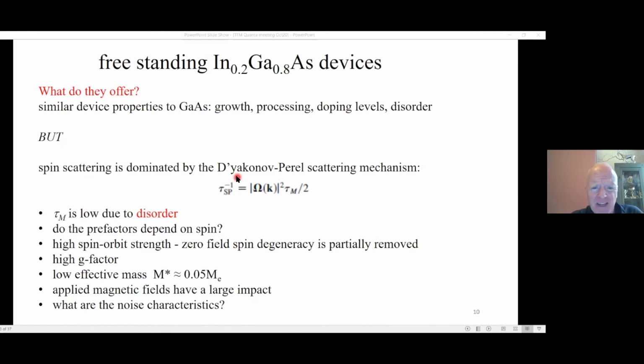In InGaAs, the spin scattering is dominated by a so-called Dyakonov-Perel scattering mechanism, and the spin flip rate, this quantity here, is determined by the spin precession from the Rashba component in the Hamiltonian, and it's also proportional to tau_m, which is the momentum relaxation time. So the momentum relaxation time can be very, very low due to disorder. That means that the spin precession rate is very low, so the spin lifetime is very long. It also may enable us to study the prefactors. Do they depend on spin?